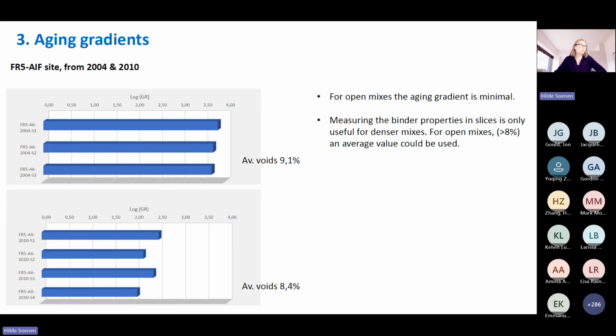If we then go to open mixes, so the two from the French side, you see air voids 9%. Now the pavement or the surface layer is aged all over. And in this case, 8.4, it still has a very minor gradient, but very little. So for the open mixes, in fact, the slicing would not be needed because the layer is completely aged.